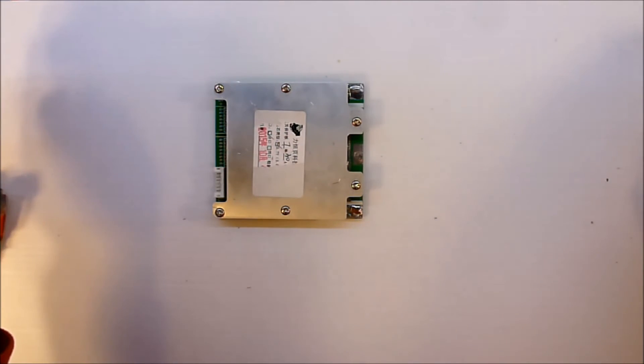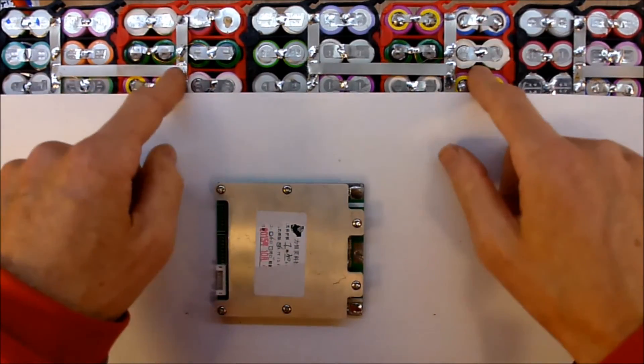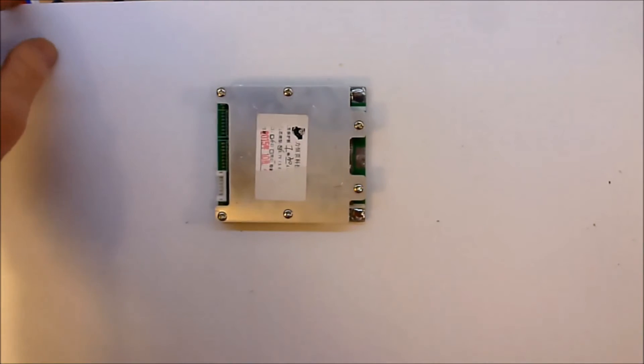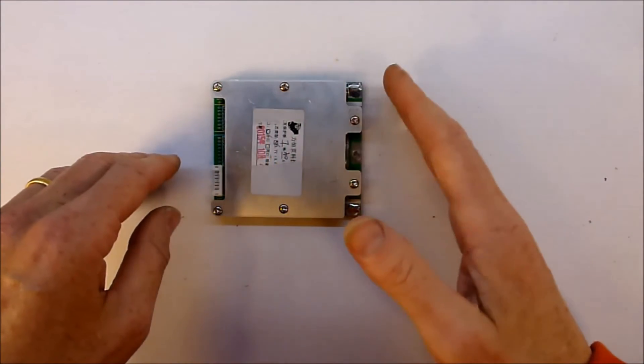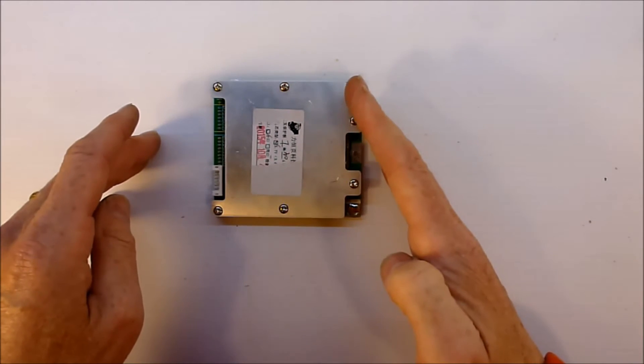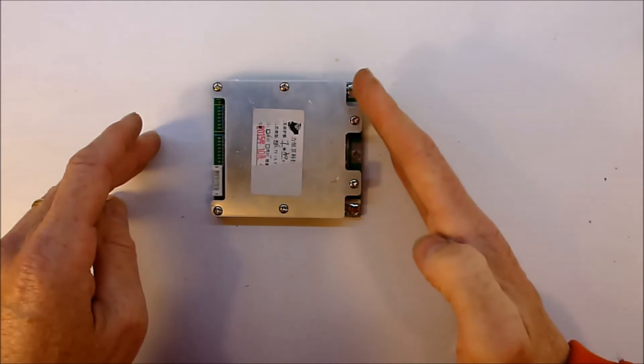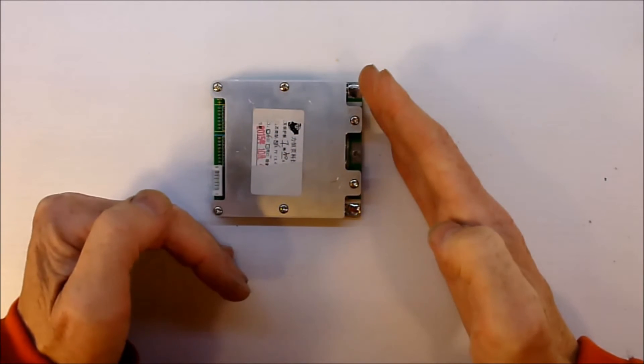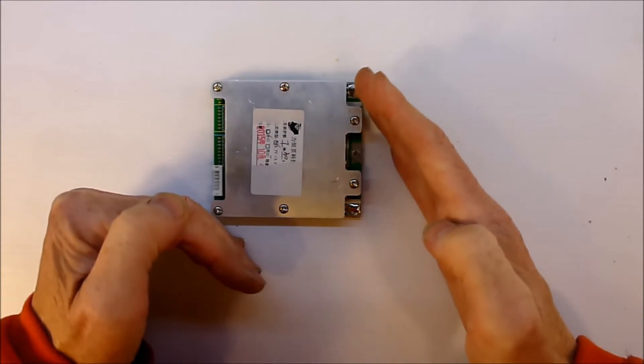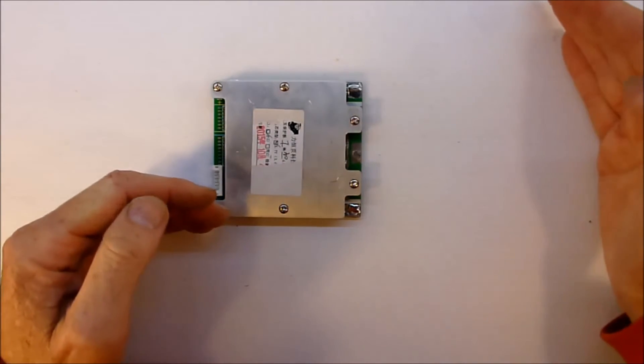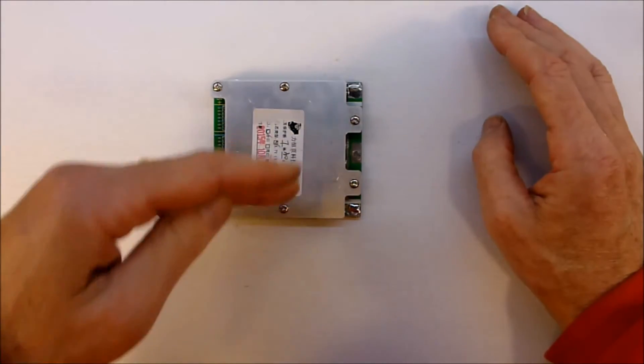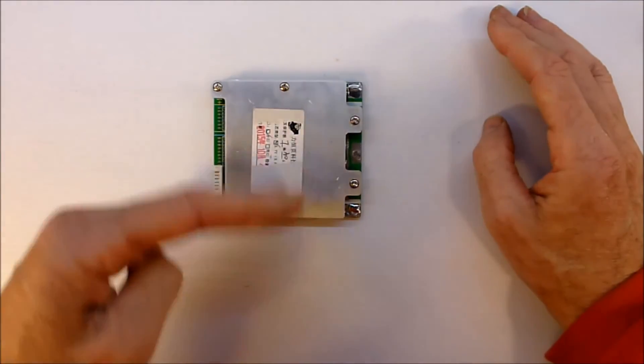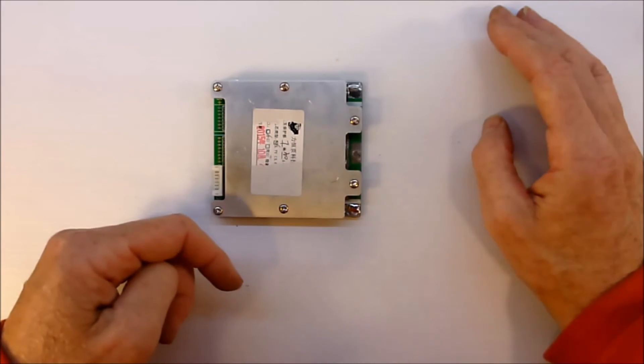If you want to go for longevity, which I'm assuming that I will want to with my power wall, I want it to last as many years as I can. Then it's better with lithium to charge it only to 4.1 or even just 4 volts, which is about 80% of its capacity. And then only discharge it down to say 40%, so that the battery is never stressed when it's being charged and is never stressed when it's being discharged. It's just humming along in that middle ground between 40% and 80% and that way you get the maximum number of charge cycles.